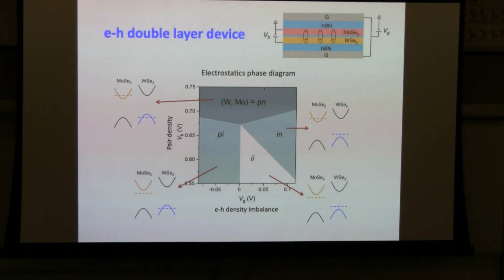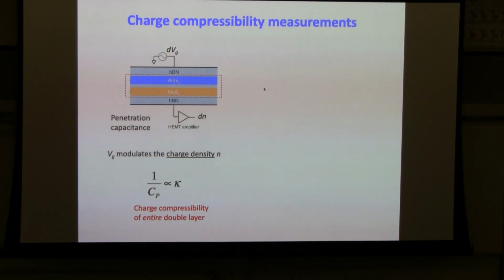The IN region is where the tungsten layer is still intrinsic, but there is now electron doping in the moly layer. That's why we call it the N. N represents an electron doping in the moly layer. The PI region would be that the moly is intrinsic, but there is hole doping in the tungsten layer. And finally, we are mostly interested in this region here, where both layers are simultaneously doped, but one by electron, one by hole, so that the band illustration is like this, electron doped in the moly and hole doped in the tungsten. Four different regions.